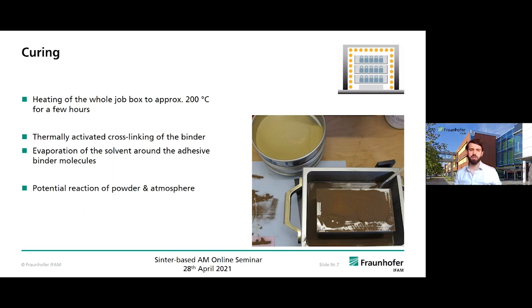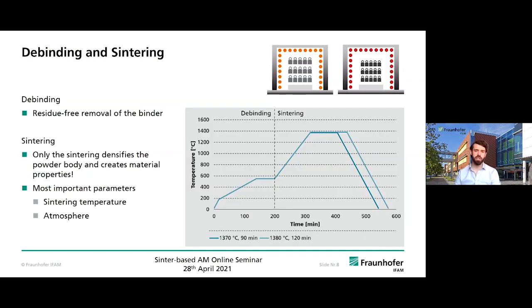After curing comes the depowdering. I guess this is not very crucial for the material development, so we can go over this step and come to debinding and sintering. When you have your green parts, you have your binder that is shaping the material and keeping the shape. You want to get this binder out, because you don't want some residual carbon inside the material. And that's the task of the debinding step. Normally we have a quite fast process, as we use a binder that burns out or goes out of the part really well, so we end with 200 minutes at approximately 550 degrees.